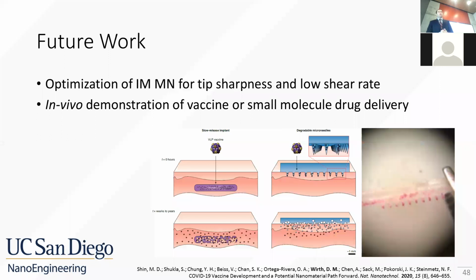So what does this mean? It means that we've successfully produced a microneedle patch fabrication process, which is potentially adaptable by future researchers. The future work in this area is optimization of these microneedle patches to be a little bit sharper and at a lower shear rate, because viral nanoparticles are very sensitive to high shear rates, especially at elevated temperatures.